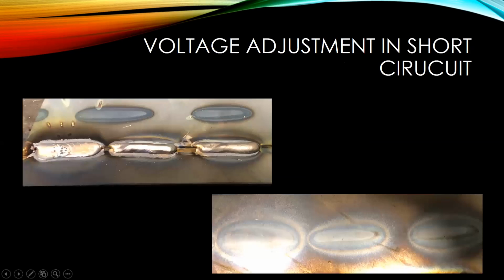I got a couple pictures here, and basically as we're looking across, all I did with these three welds is I adjusted my voltage slightly. The first weld here, I just called a nominal setting. I just dialed in the arc, had it nice and smooth. Then moving over to this weld, I dropped my voltage about 2 volts, and what you can see is it got a little more ropey, a little more buildup, and didn't quite wash out as much on the toes. And then on this third weld, I really increased the voltage, and you can see that puddle just washed out a lot. It also had an effect on how much steel it drew into that weld puddle.